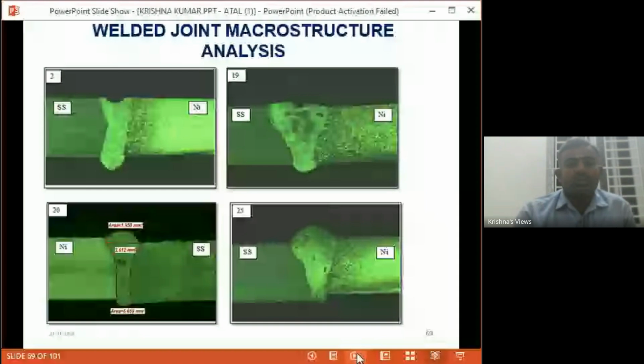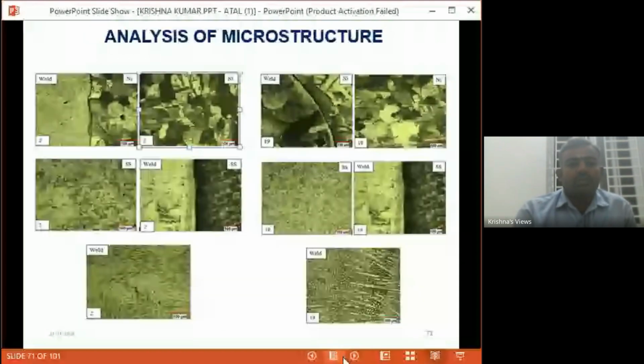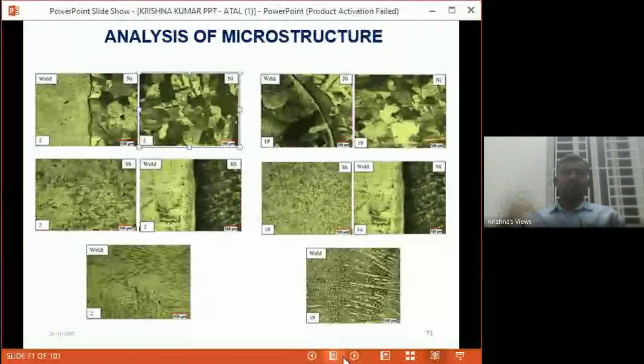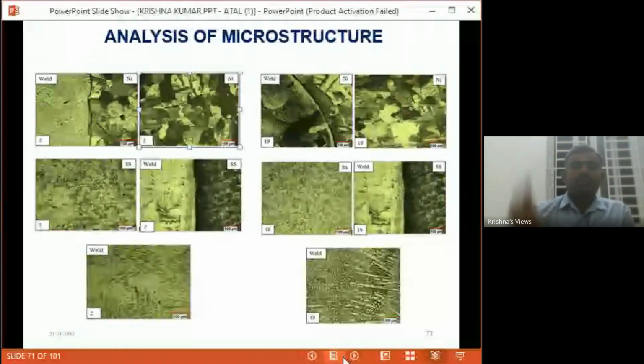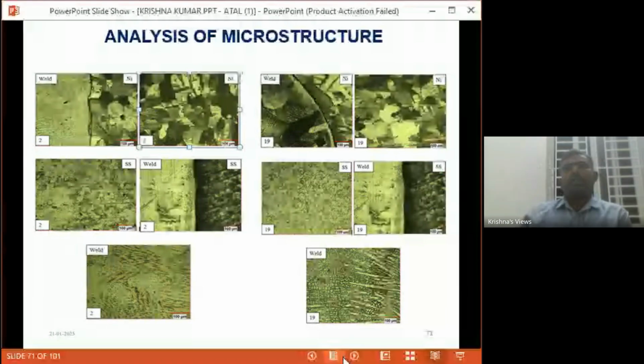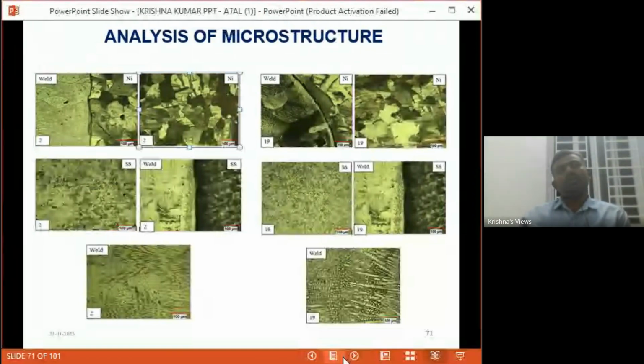No, porosity should be there. Porosity is there, but it should be within a limit. If there is more porosity, that too leads to joint failure. If it is more porosity, the reason may be the speed. If you are seeing more porosity in all the trials, nearly 30, 40 plus trial runs, then we should control the speed.